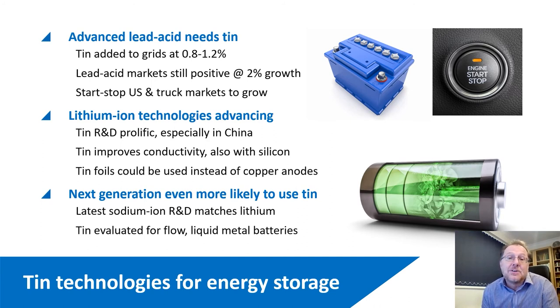Technologically, tin improves the conductivity of the anode and electrolyte. And as you will hear a lot about silicon in lithium-ion batteries, I know Tesla announced that recently. Well, tin alongside silicon is synergistic. So we may not hear about it so much, but tin certainly works well with silicon as an additive. And we've seen some very interesting work recently coming out from various places on tin foils used in the anode. At the moment, the anode is a copper foil with carbon, but in fact, the whole assembly could be replaced by tin. So those papers are interesting, and we're watching that space very closely to see if we can find any evidence of commercial use, and we'll certainly let you know when we see that.